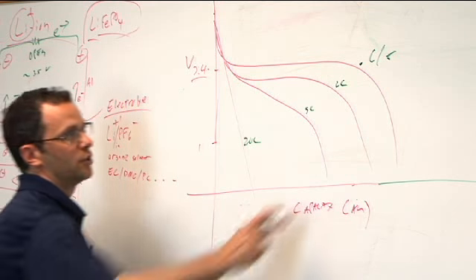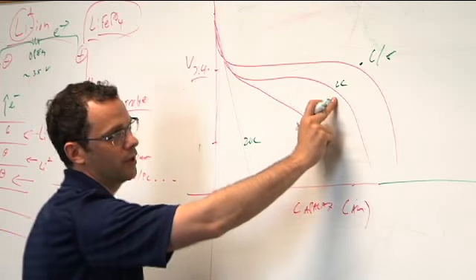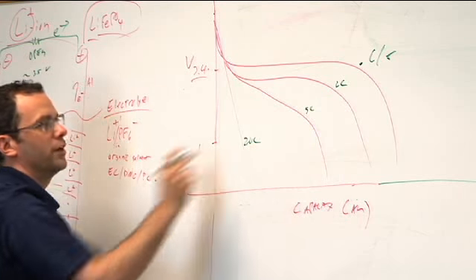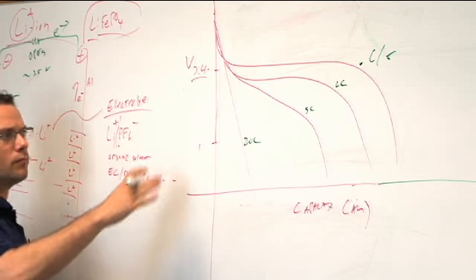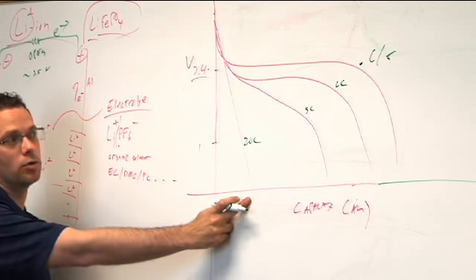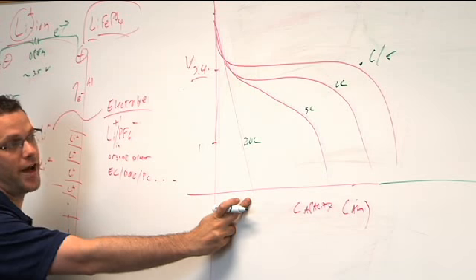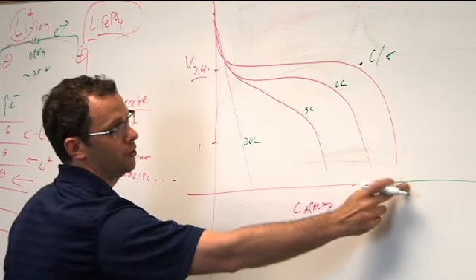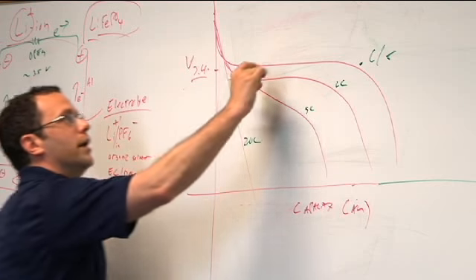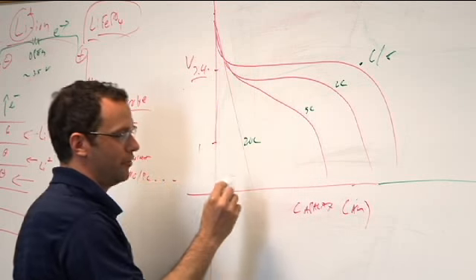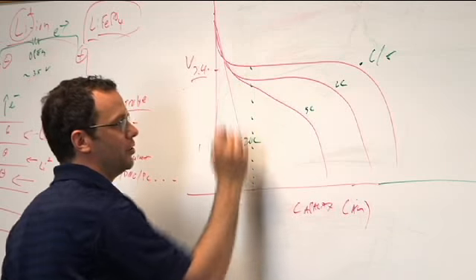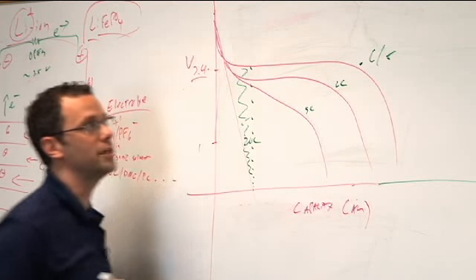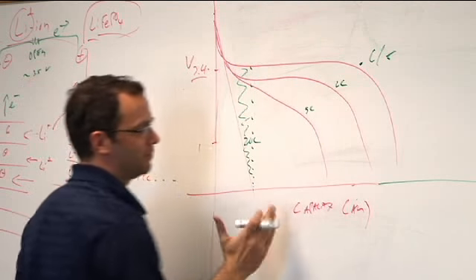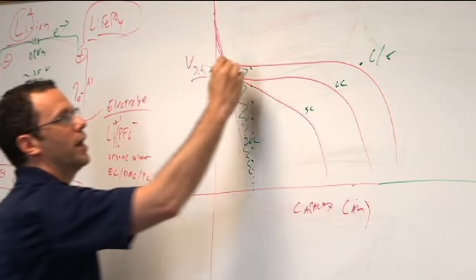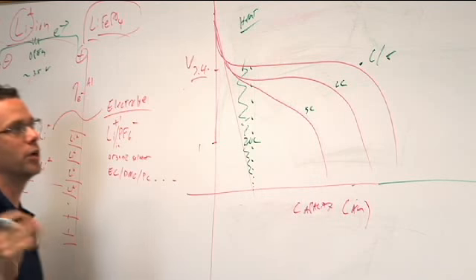So it took me 5 hours to get this data, and I did the same thing at 2C, so half an hour, shorter, and very short. So you can see I get much less energy out when I do the super fast, high current, as opposed to this very low current. And concurrently, whatever capacity you get out, you drop this much energy as heat. This is like my equilibrium curve. Anything above it that you're not realizing in the amount of time through which you are discharging goes away as heat. Okay, and heat is bad, and I'll tell you why in a minute.